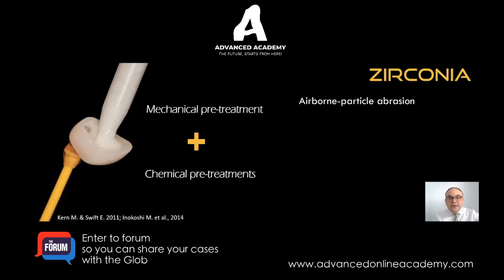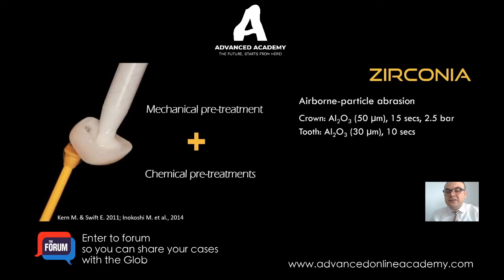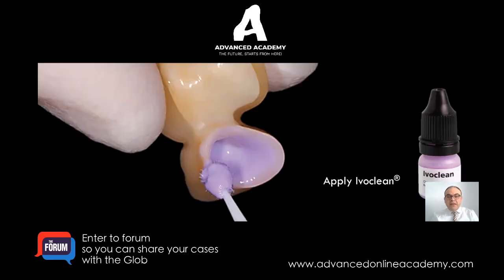You're going to do airborne particle abrasion of your zirconia restoration, with 50 micron sandblasting for 15 seconds at 2.5 bar pressure. The time of the sandblasting plays a very important role. You can intraoral sandblast with 25 to 30 micron sand particles for about 10 seconds. And then for your chemical pretreatment, you add a ceramic primer. Usually the primers have silane and also the adhesive containing the MDP monomer, which is going to enhance the chemical bond to the tooth structure. Always use Ivoclean.